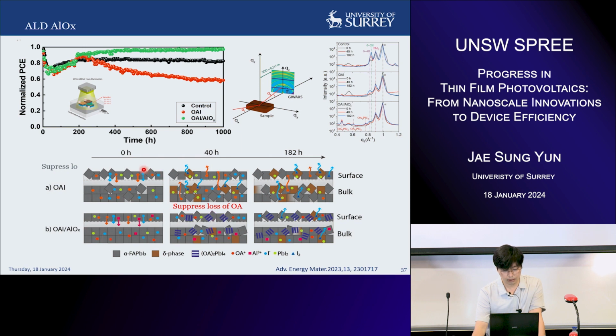So we studied this using GIWAXS and found out that for the control sample, there are going to be a lot of delta phase and loss of the A-site cations, and that results in lead iodide phase. The same case happens with OAI. However, you can see that with OAI and aluminum oxide, continuous illumination actually forms a very nice 2D layer on top of your perovskite.